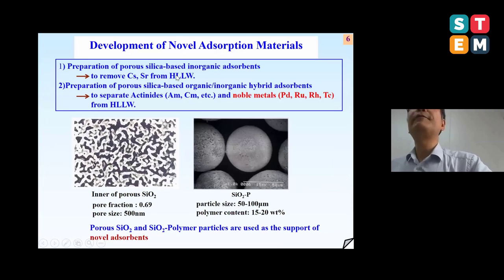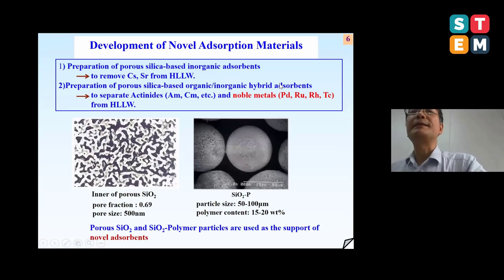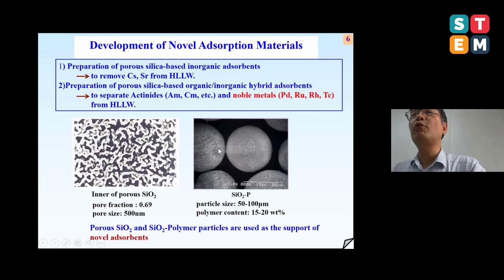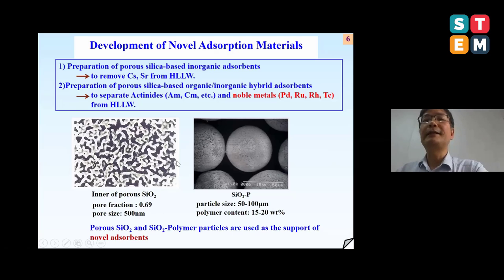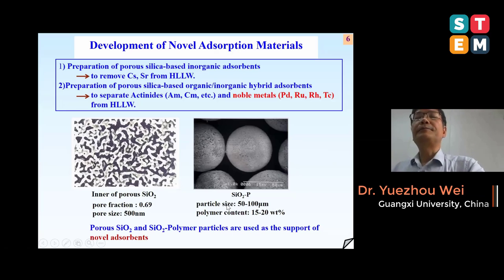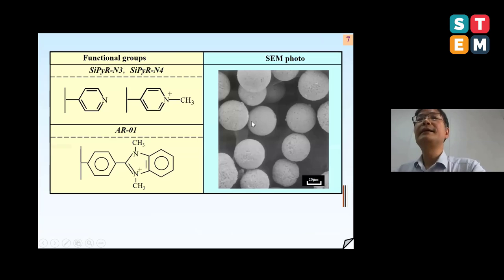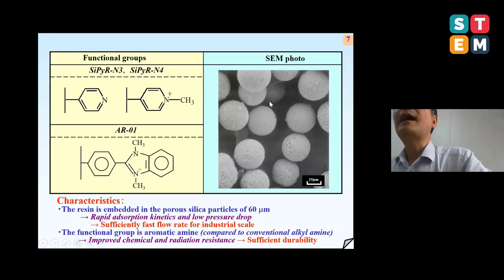We prepared a novel absorption material — we call it the organic-inorganic hybrid adsorbent. We use very highly porous silica particles as the support for the organic ligands. The silica particles have a very small particle size, less than 100 micrometers, but the pore size is very large, around 500 nanometers, and the pore volume is very high. So we can load the organic ligands into the big pores of the support and obtain new types of ion exchange ligands.